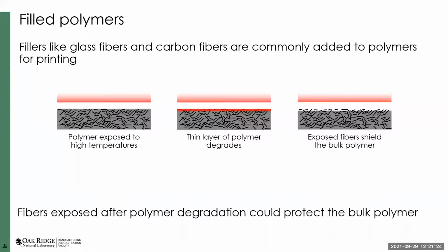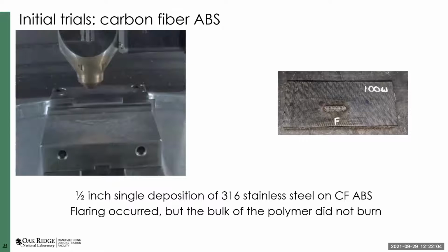The idea behind this is that you have a polymer embedded with a bunch of chopped fibers, whether they be carbon fibers or glass fibers. When you expose your polymer to both the laser and the molten metal, you do degrade a thin layer of polymer, say ABS or nylon. But by the degradation of that polymer, you expose a layer of previously embedded fibers that can resist much higher temperatures than the polymer on its own. Once you have these exposed fibers, they can shield the bulk of the polymer from the thermal effects of the process. So that was our hypothesis. And then we got in and ran some trials.